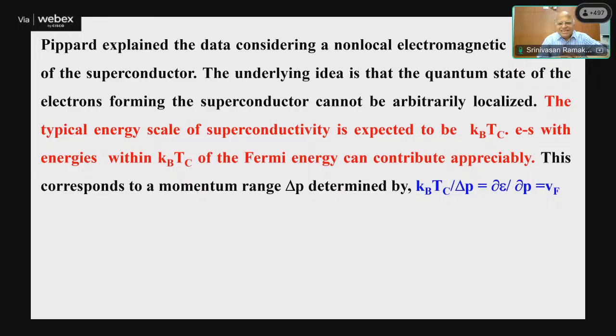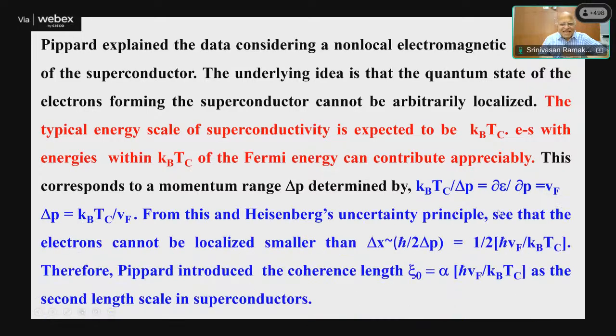So the underlying idea is that the quantum state of the electrons forming the superconductor cannot be arbitrarily localized. The typical energy scale of superconductivity is expected to be kBTC, and the electrons within this kBTC in the Fermi level will contribute appreciably to the superconductivity. And we can see that kBTC is the energy, and divided by the momentum, it is the Fermi velocity, and the delta P is kBTC by Vf. So from the Heisenberg uncertainty principle, we can see that delta x cannot be localized more than this. Delta x will be something like this. And from this, he introduced the coherence length, which is proportional to h cross v by kBTC.